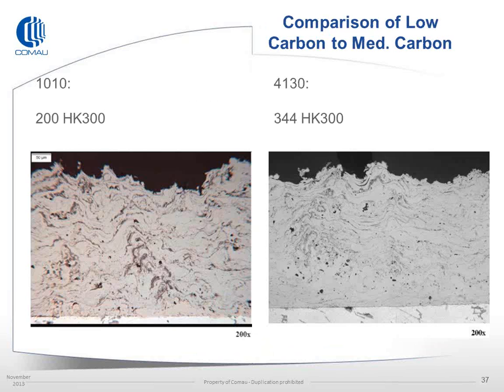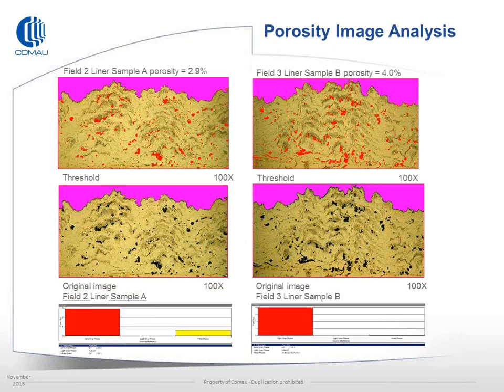The flexibility of the system, like I said, is that we can spray a 4130. The hardness created by spraying 4130 or 1010 with air changes based on the carbon content. So with the higher carbon content and alloying phases of 4130, we get an increase of approximately 60% in hardness. Part of this hardness issue is what creates post-machining issues for boring, and why we recommend going with honing. The porosity is fairly well random. It's almost a random homogeneous distribution. So the coating will have similar porosity throughout its depth and across the length of the coating.